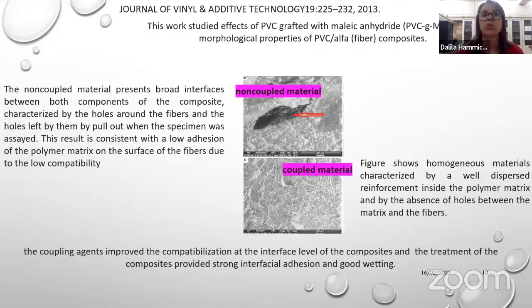But when we use the coupling agent, as it is clear in the second figure, we can see homogeneous materials characterized by a well-dispersed reinforcement inside the polymer matrix and by the absence of holes between the matrix and fibers. This result clearly demonstrates that the treatment of the composite, or the use of PVC-GMA as a coupling agent, provides a strong interfacial adhesion and a good wetting between fibers and matrix.